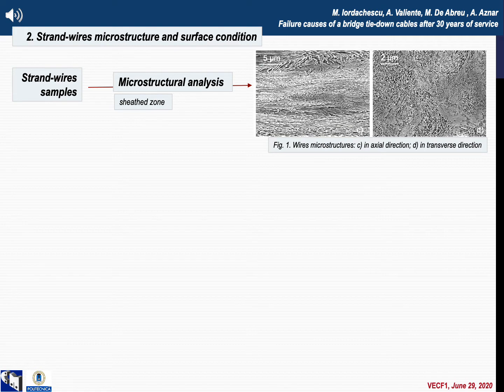The microstructural analysis of the broken strand steel was made on metallographic samples extracted from the strand's end protected by the polyethylene sheet. The wire's microstructure in longitudinal direction consists in axially oriented fine perlite colonies. In contrast, in transverse direction, the perlite colonies are randomly oriented and the cementite lamellas are considerably smaller in length, or when larger, have a curled form. These differences in the microstructure induced by cold drawing are indicators of mechanical anisotropy, particularly of fracture resistance, that determines the failure mechanism of this wire steel.